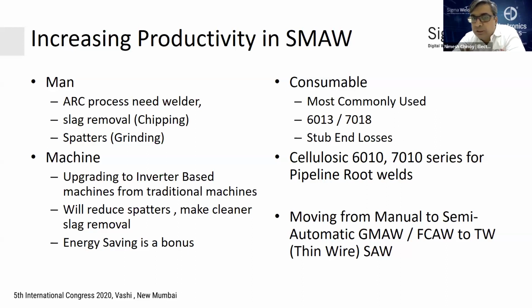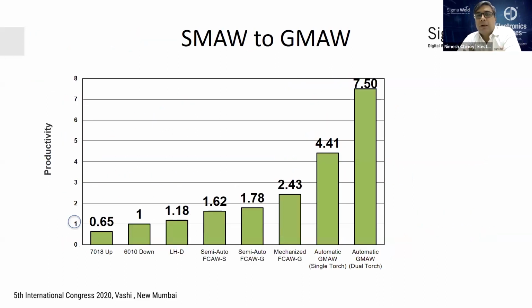Most commonly used electrodes are 6013, 7018, and for pipeline root welds, they use cellulosic electrodes such as 6010, 7010. If you're using arc welding, you can move over to manual or semi-automatic MIG-MAG, flux core wire, or thin wire SAW to increase your productivity and efficiency. If you move from arc welding to MIG-MAG welding, for the bottom first 3 electrodes that you see, 7018, 6010, and low hydrogen, you can see the deposit rates between 0.65 to 1.18 kgs. And if you move upwards towards semi-automatic flux core welding and all the way up to automated MIG-MAG dual torch, you can go up to 7.5 kgs per hour.